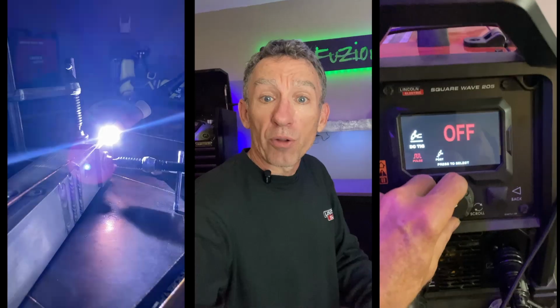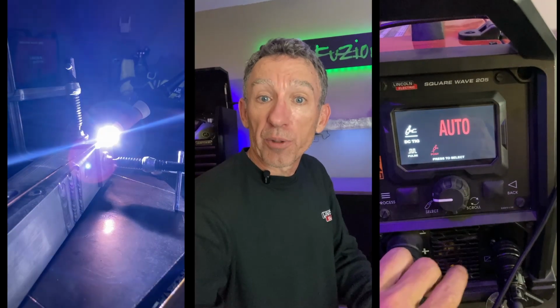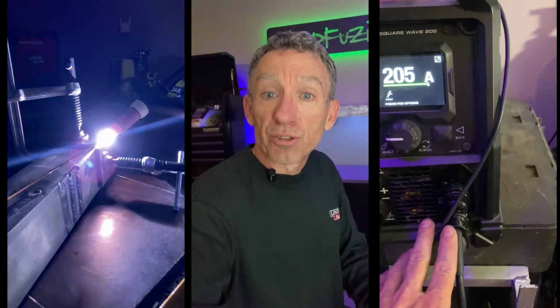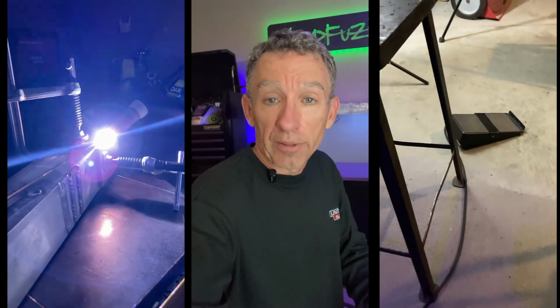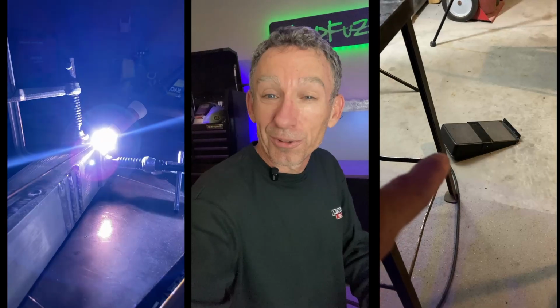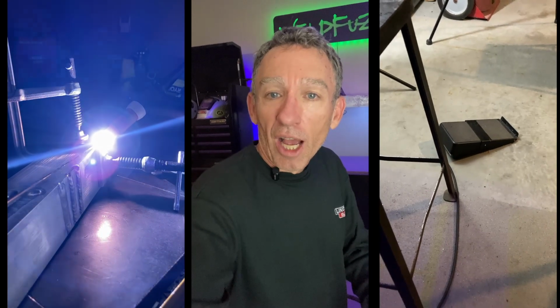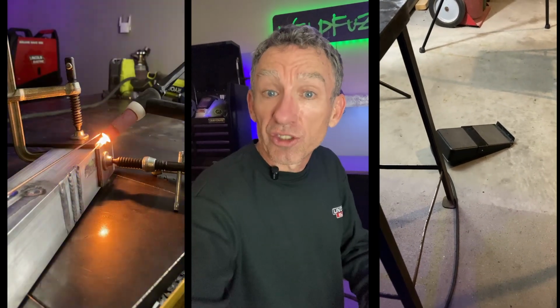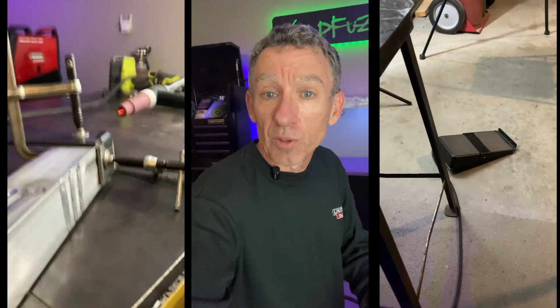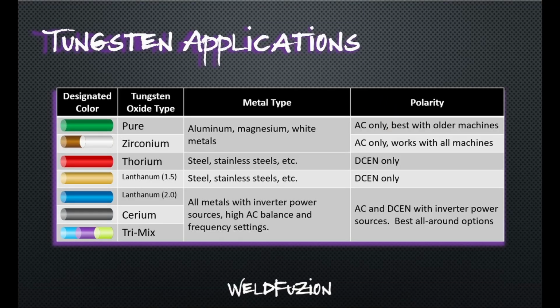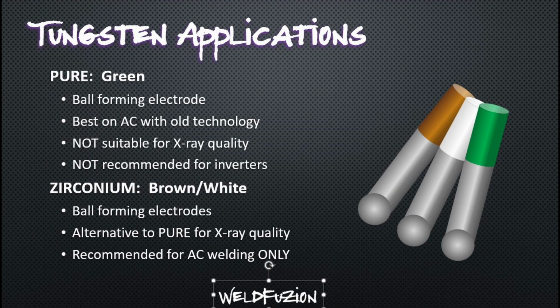Okay, so as a recap here, we used DC TIG, no pulse, and automatic post flow. I was running 100% argon at about 20 cubic feet an hour. We used 1/16 ER70S-2 filler rod, which had a copper coating on it to prevent oxidation of the rod between welds. And at the same time, I was using 3/32 2% ceriated tungsten. Any DC tungsten would work. Cerium works fine. Lanthanum works fine. Of course, you can use the purple tungsten, not the green tungsten, anything but the green tungsten. Unless you're talking about that odd chartreuse color, something about a laser tungsten. So that's where we're at.